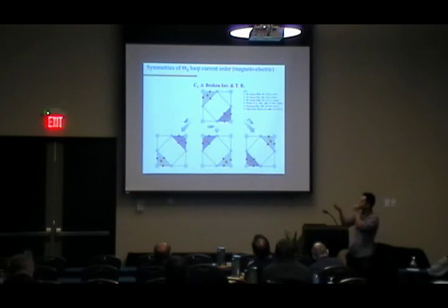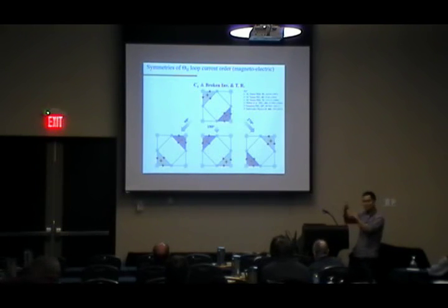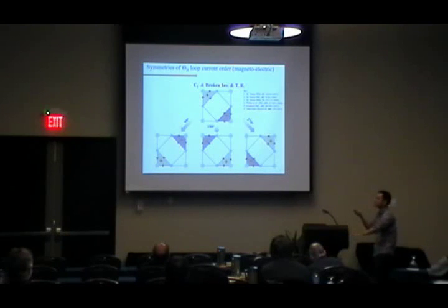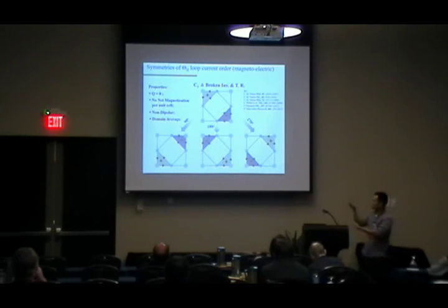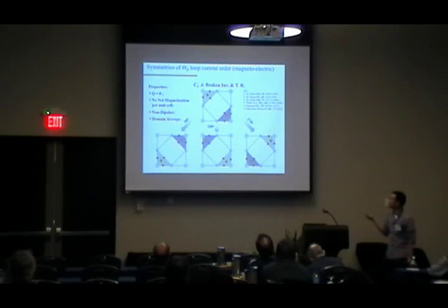The problem with this sort of phase that has plagued other measurements is that naturally you expect four degenerate ground states. So if you perform any sort of sample-averaged measurement, you're not going to see the symmetry break, because if you average over all of these, the fourfold rotational symmetry is maintained. Beyond that, this is hard to measure for other reasons. It's Q equals zero, it doesn't break translational symmetry, there's no net magnetization, and as I mentioned, there's this domain issue.